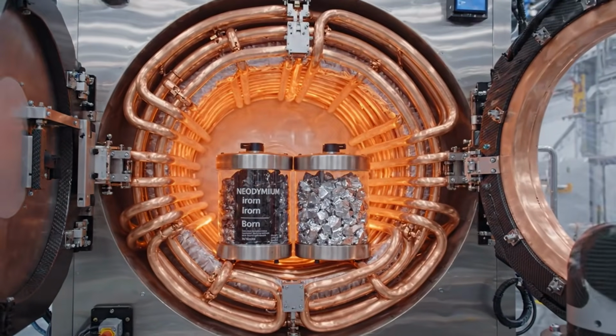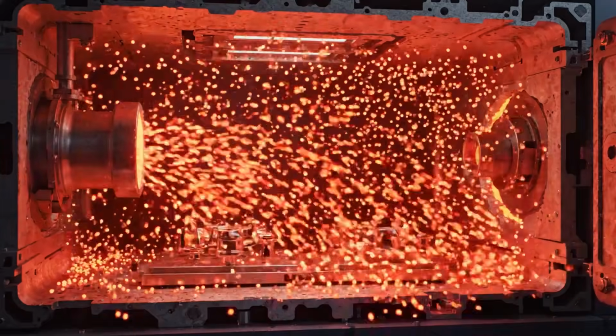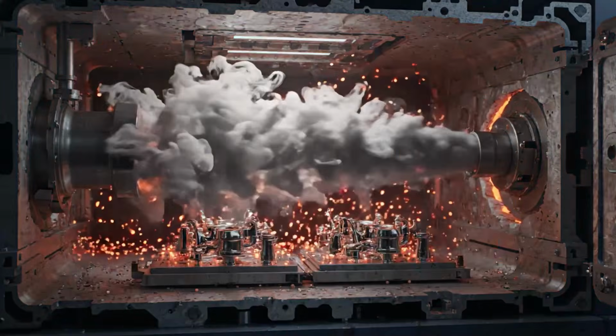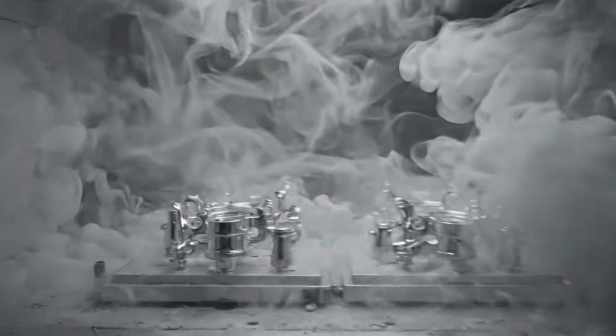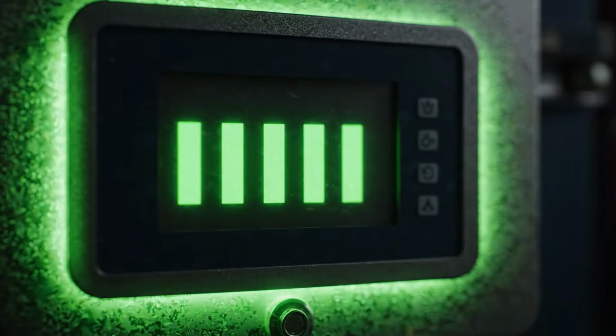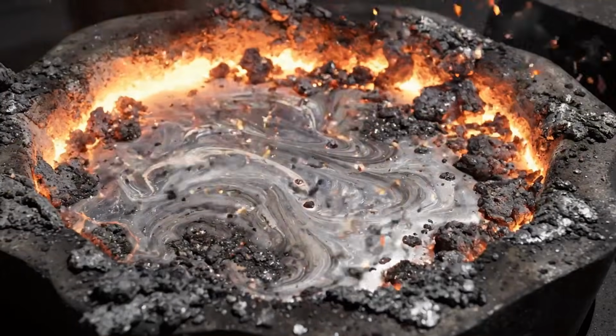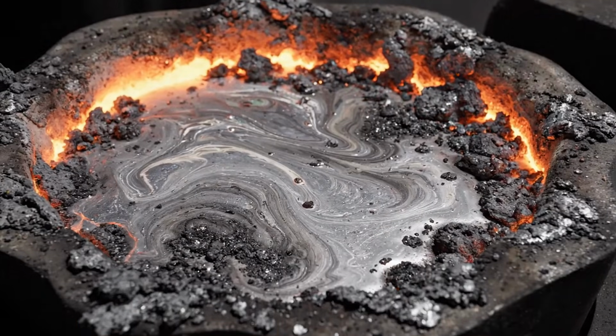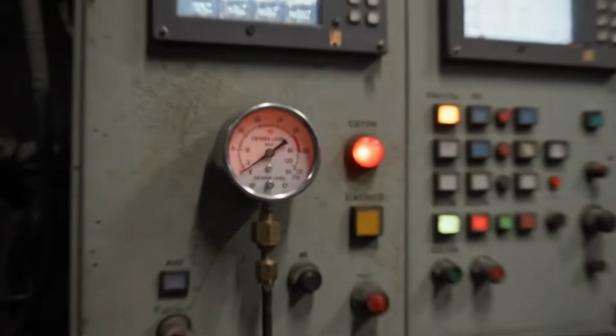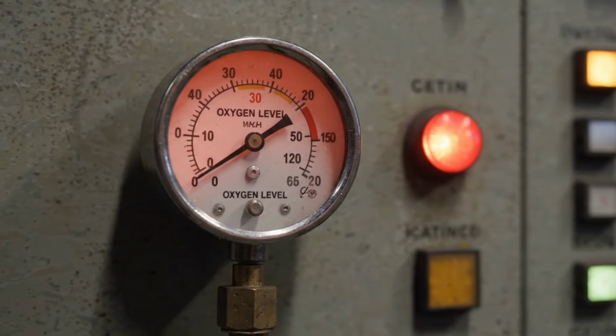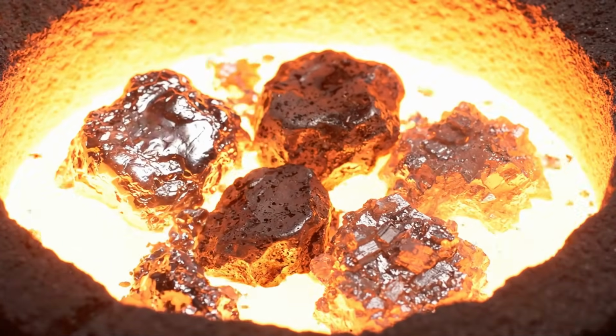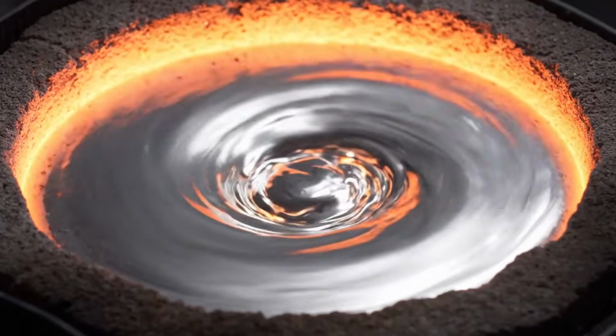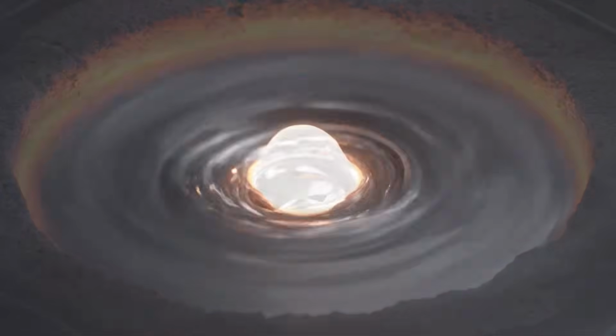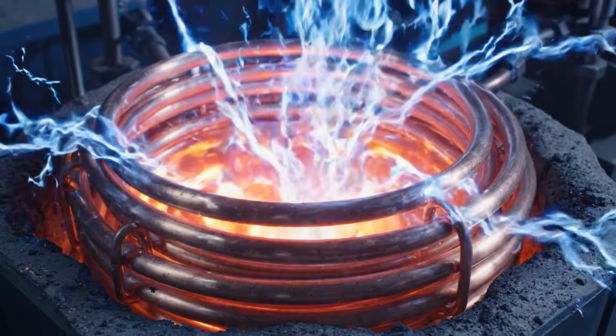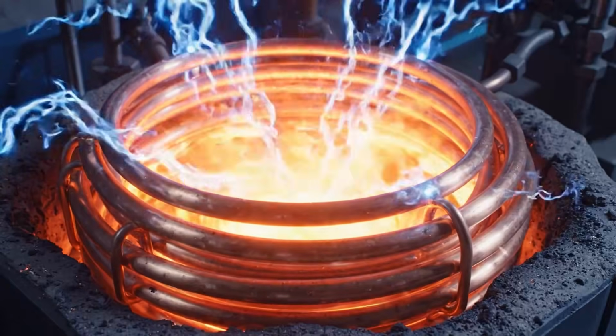After pressing comes sintering. This stage transforms the compacted powder into a dense, durable material. The parts are placed in sealed furnaces where the temperature is raised in a controlled manner. For neodymium magnets, sintering is carried out in a vacuum or an inert atmosphere. The heat allows the particles to bond together without melting completely. Their surfaces soften, diffuse, and form strong bonds. At the same time, internal pores are reduced, and the density increases to approach that of a solid metal.